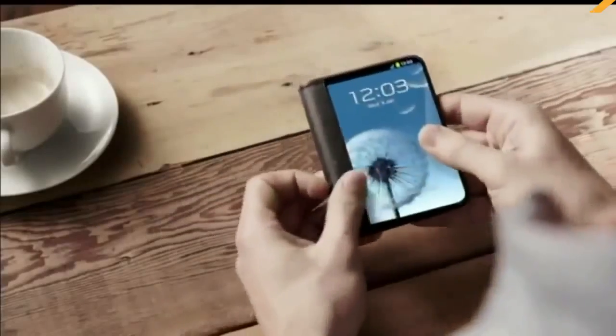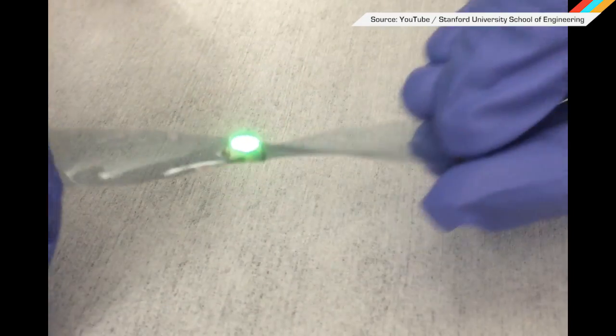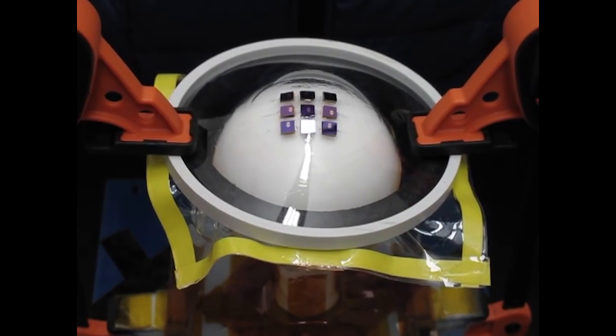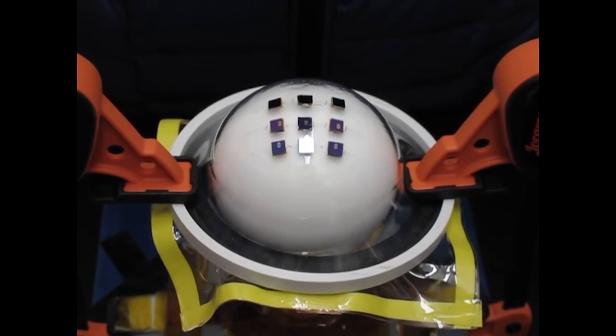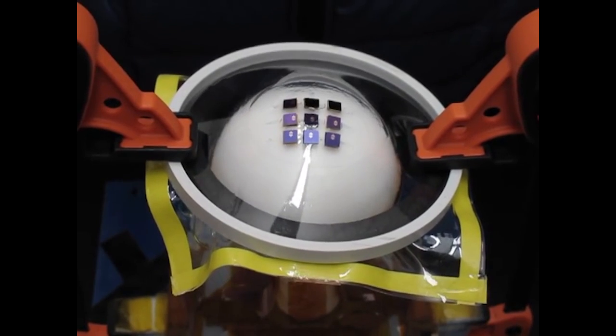Bendable phone screens are only the beginning. For electronics to start being integrated into our clothes and our bodies, we need conductors that can bend and flex without breaking. And that's exactly what a team of Stanford researchers have developed using a surprising ingredient: soup thickener. The team first created a clear plastic electrode using a pair of conductive polymers. They then teamed with researchers from the SLAC National Accelerator Laboratory to find a compound that would prevent the polymers from crystallizing and provide the electrode with a bit of give. They found it in a molecule similar to those used in commercial kitchens for thickening soups. The result is a deformable plastic that actually conducts electricity better the more you stretch it.